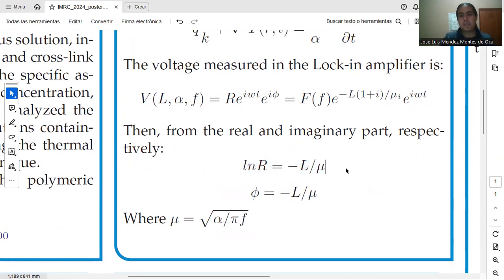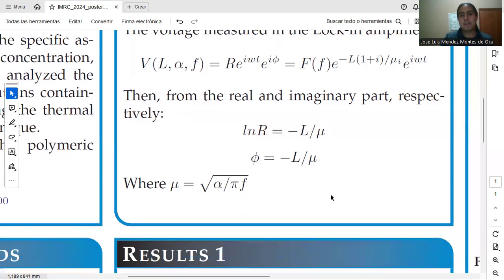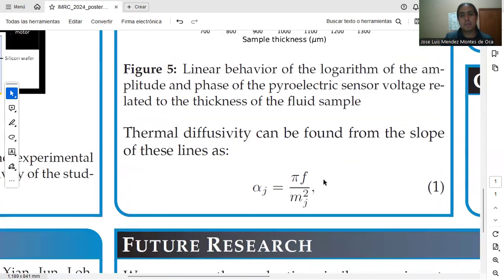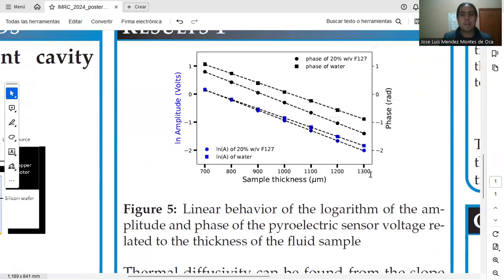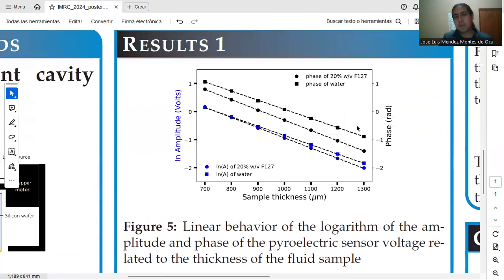And from the slopes of these lines, it is possible to obtain the thermal diffusivity of the material, because it's inside the parameter mu. So using this equation, where m is the slope of the curves, it is possible to obtain the thermal diffusivity. And this is a result of common experiments.